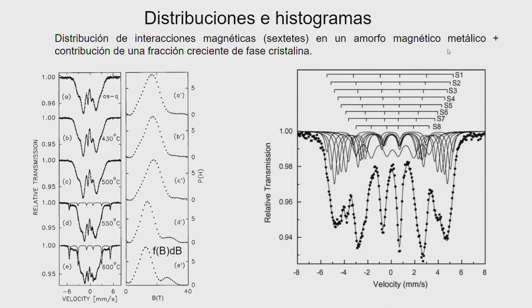And then you need many, many subspectra in order to give account of your spectrum. And this can be done, as in this case, by putting many subspectra with some restrictions, or you can also use a distribution of hyperfine fields, just a function with a distribution of hyperfine fields, which usually needs to take into account certain correlations between the distribution of hyperfine fields and the distribution of isomer shifts, okay? And also correlation with the quadrupole interaction.